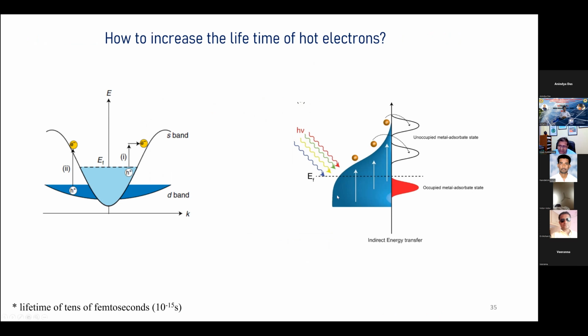So what we decided was to make some sort of heterojunction, some sort of bimetallic system, where in one metal, which is black gold, once the electrons are generated, they jump and get injected, transferring into the unoccupied state of another metal. So electron is in one metal, hole is in another metal. They are separated. That should ideally increase the lifetime and allow you to get better catalytic activity.